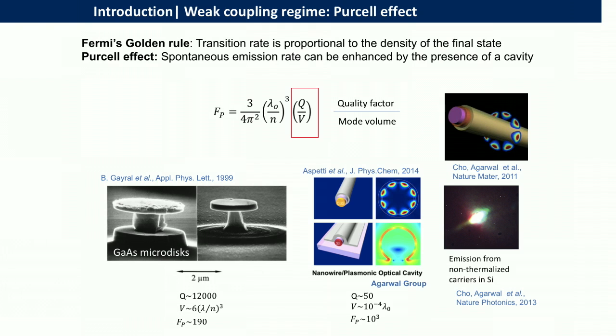So what we did, many years back, and I won't talk about this in too much detail, what we found was by combining some attributes of surface plasmons, but not localized surface plasmons. We took a nanowire made out of semiconductor, and then we conformally wrapped a plasmonic metal. At the interface of a semiconductor and a metal, one can launch surface plasmon modes. And because this is a cylindrical structure, at certain sizes one can have constructive interference of the mode, and we can create these highly intense whispering gallery modes at the interface of a metal and a semiconductor, because of which we could get Purcell factors of the order of 1,000.